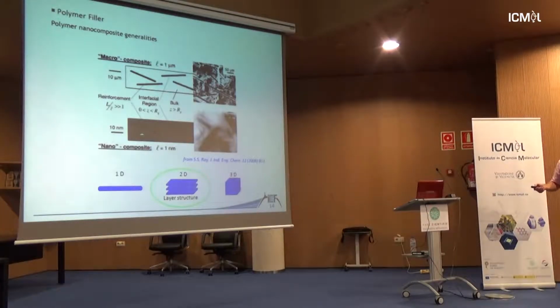When you go down to the nanometer scale for the filler, the interface is preponderant. It means that the interaction between the filler and the polymer chain is dramatically enhanced. So you cannot foresee, you cannot calculate anymore what you will have at the end, because the interaction is in fact the best part. That's the gluing together between polymer chains, between the gyration radius of your polymer chain, contacting directly the surface of your composite.